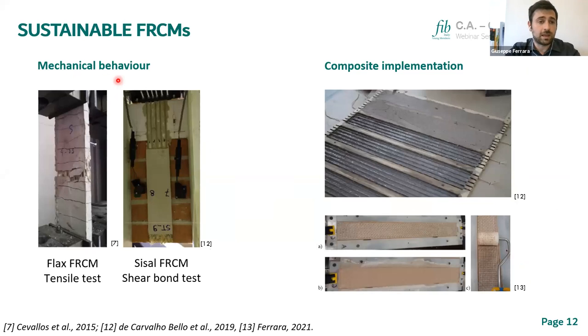So if you look at the mechanical behavior, several studies focus their attention on the flexural and tensile tests of natural FRCMs as well as shear bond tests. In this sense, we have to focus the attention on the composite implementation, because it's not as easy as it is with traditional composites, because normally you have this textile that is really flexible. And so the installation is quite a critical aspect, because we have to guarantee the textile to be as tight as possible in order to work properly with the matrix. And so we also have to take attention in pressing the textile over the mortar in order to guarantee a correct penetration of the textile within the mortar.